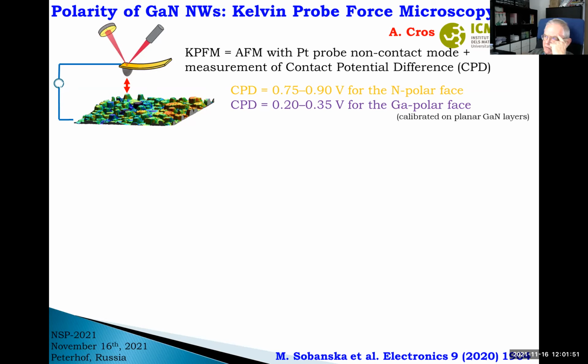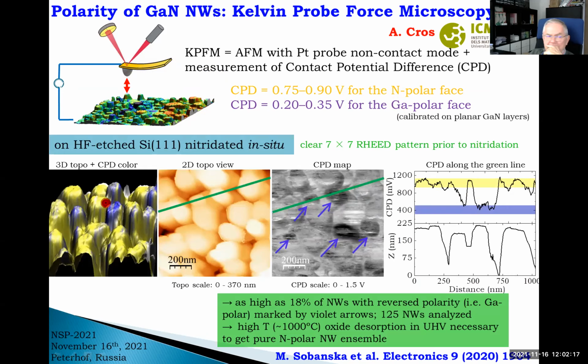So what we did in cooperation with Anna Cros from Valencia, we grew some samples, and then Anna analyzed them by using Kelvin probe force microscopy, which basically measures a contact potential difference between the tip and the nanowire. And two values are expected for nitrogen and gallium polar faces. And this is the experimental result.